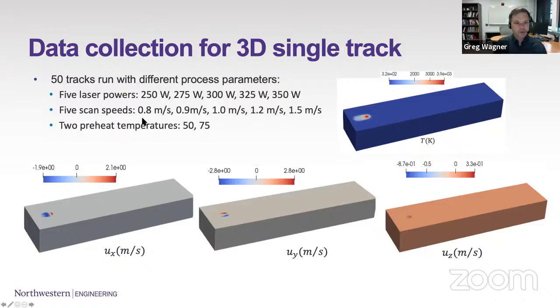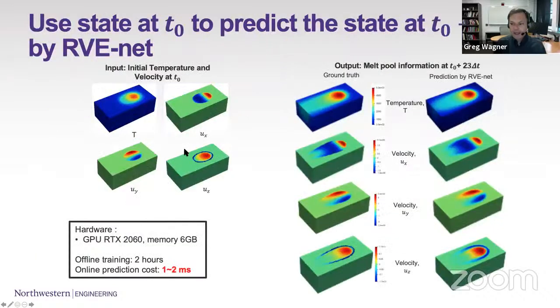And we're running with a range of different laser powers and scan speeds that would be significant for a typical powder bed process. And we can increase the range of process parameters. We're getting temperatures and velocities for each of these and using these to train our simulations. And this is what the results look like. Again, these are just preliminary results, but overall, we're really happy with this.